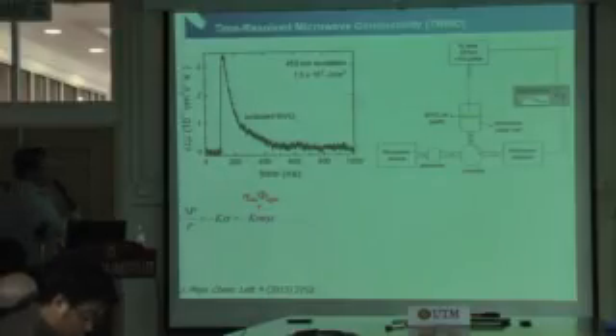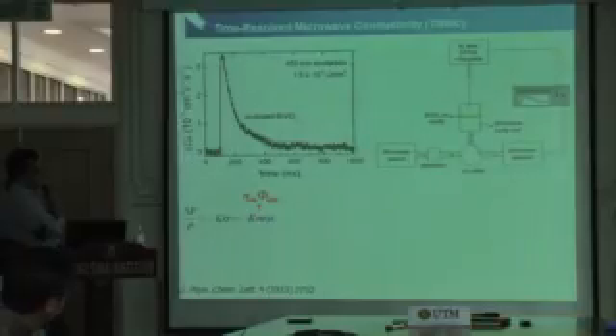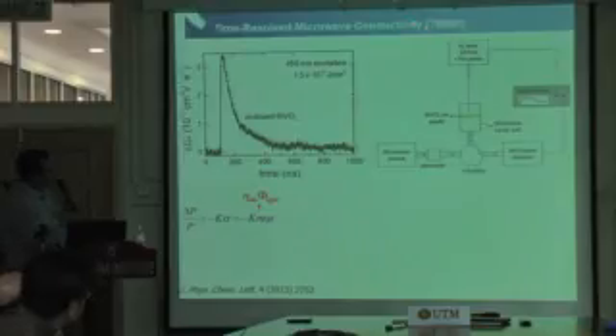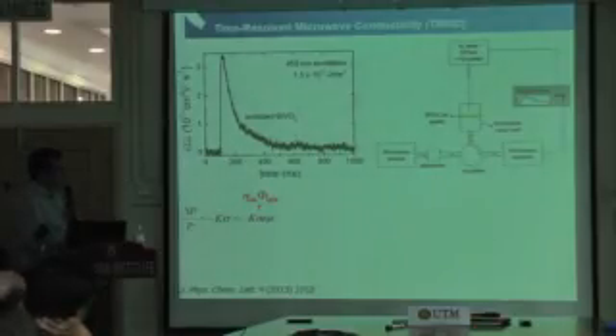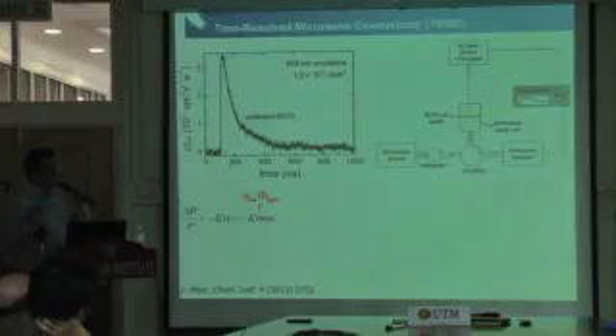To also understand the reason behind this poor charge separation, we performed a technique called time-resolved microwave conductivity, or TRMC in short. It's depicted right over here. Basically, you put your sample in a microwave cavity cell, and then you excite it with short laser pulse illumination, so you create electrons and holes, so you create mobile carriers. And then from the back here, you send a microwave signal, which goes that way and then back to the detector. What the microwave will do is interact with the mobile carriers. So mobile carriers can absorb microwave.